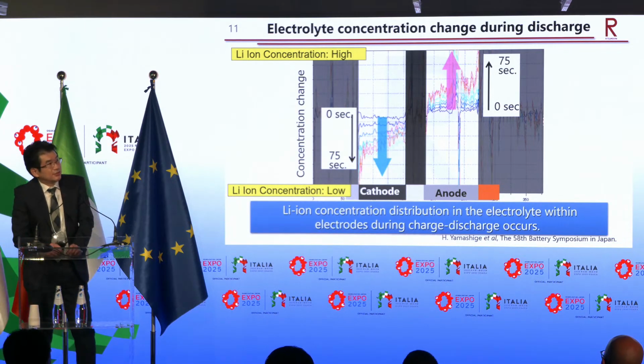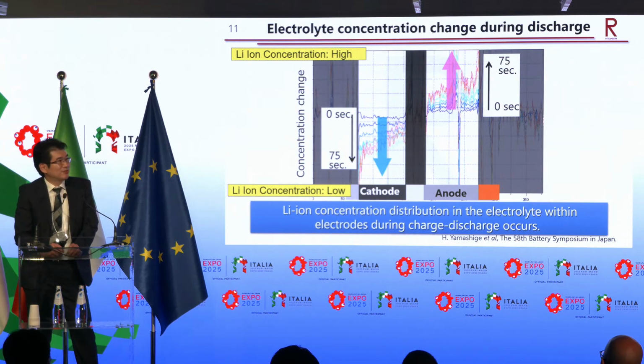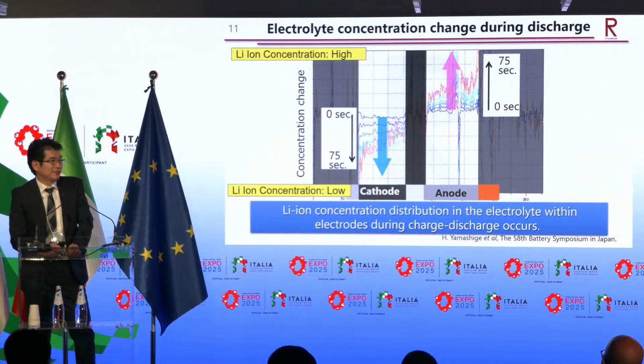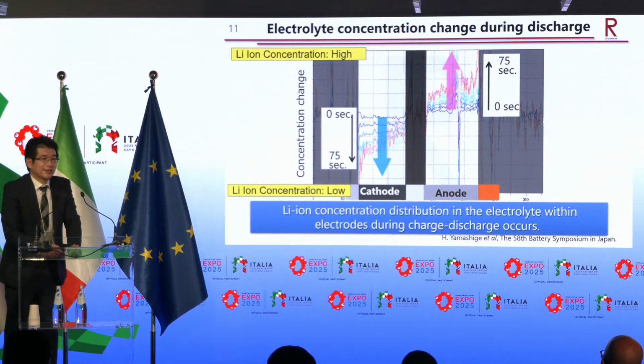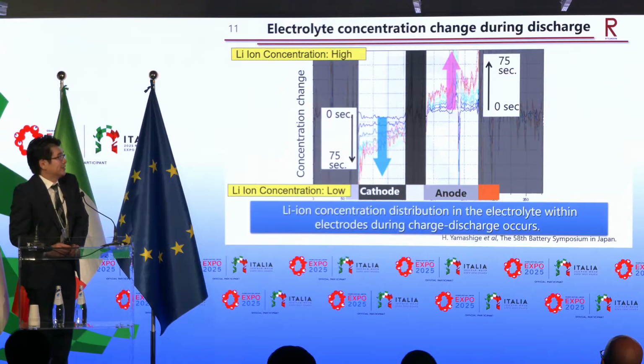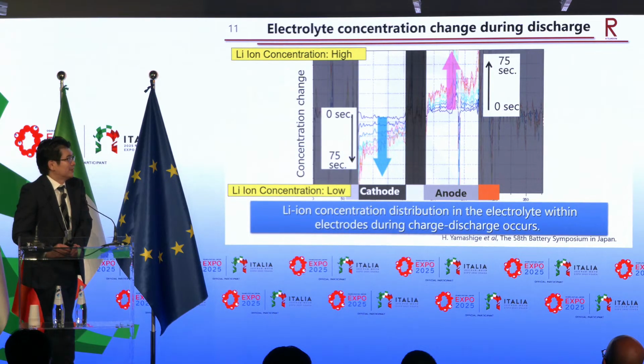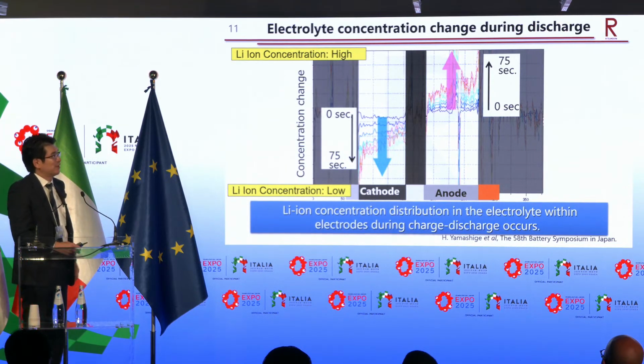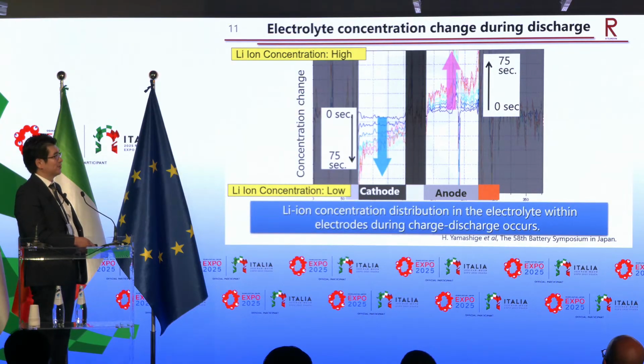This phenomenon is maybe not detected in the water-based electrolyte, because basically the conductivity of water electrolyte is much higher than the organic electrolyte. For the lithium-ion battery case, the organic electrolyte is used, and maybe many phenomena are slow compared with the water-based electrolyte.